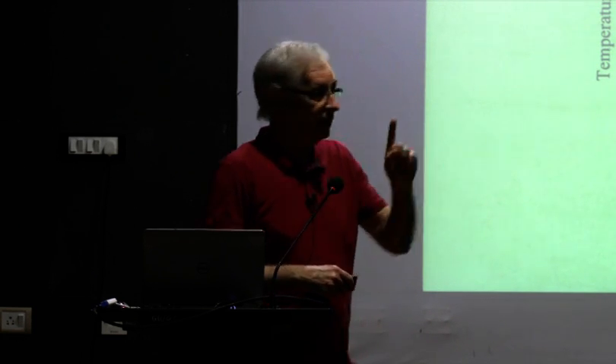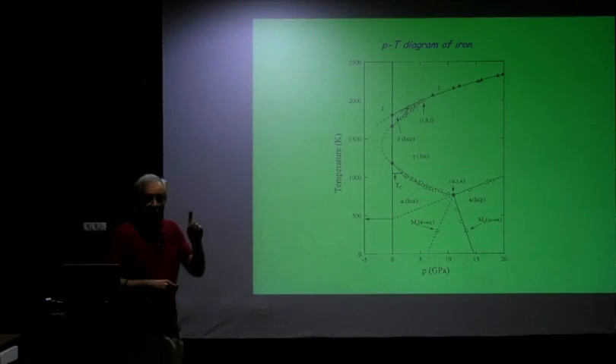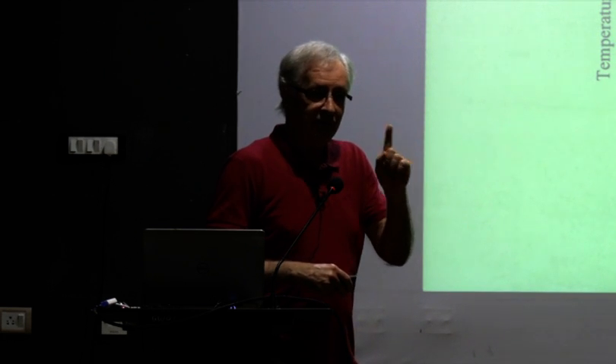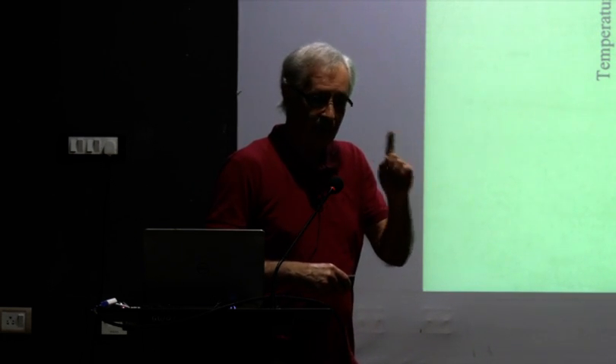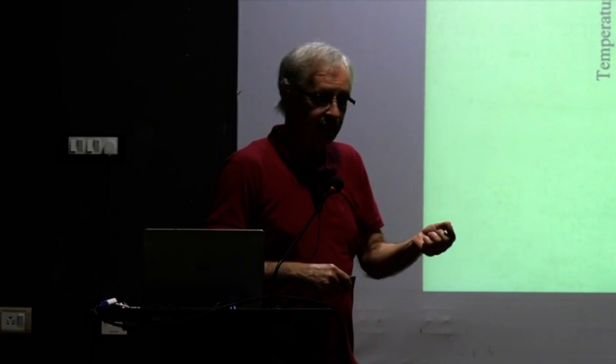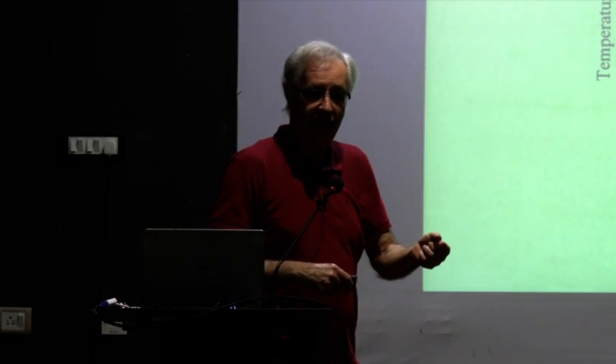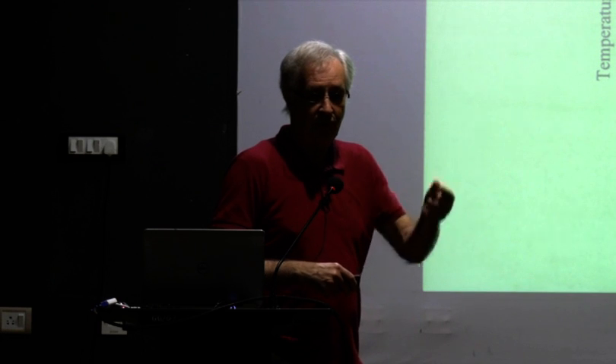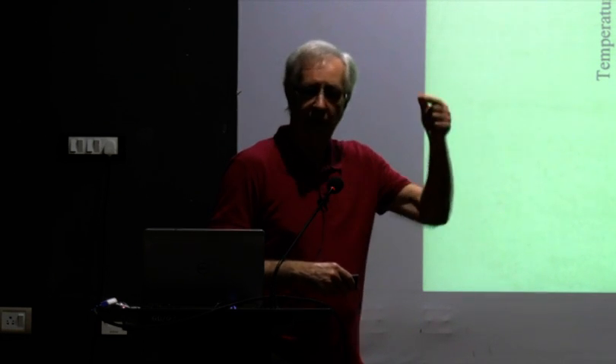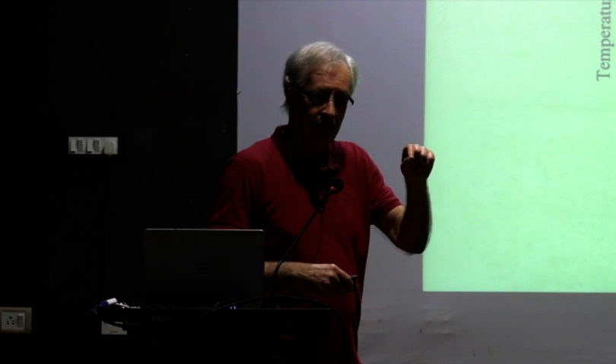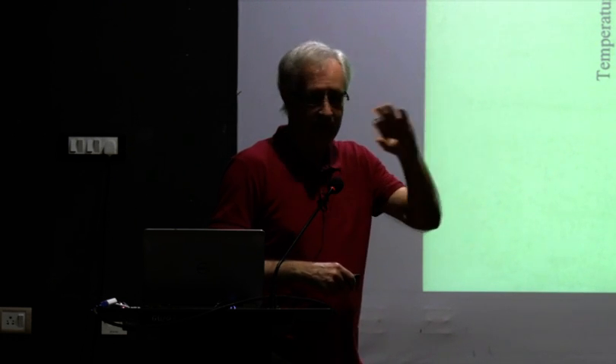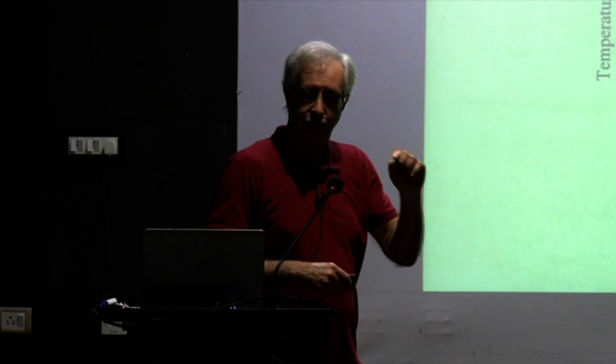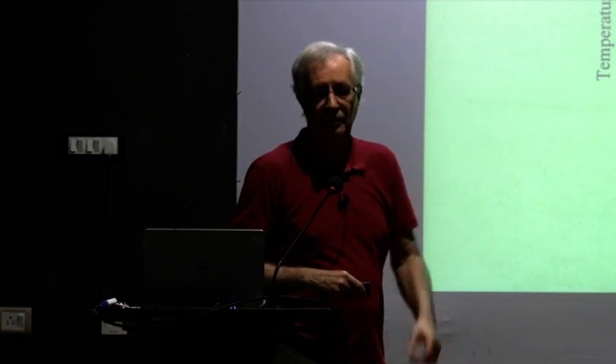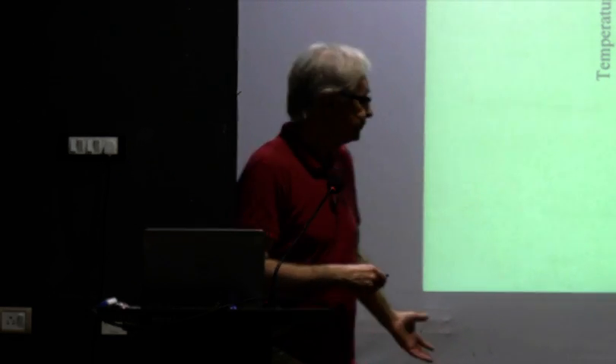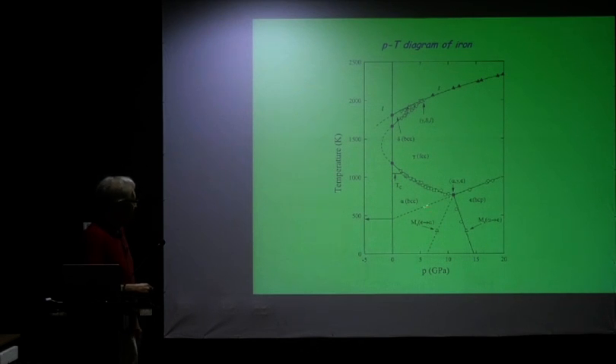So what happens then? It is the magnetism that stabilizes the BCC state. And if we don't have magnetism, the hexagonal state is stable, and everything on the periodic table is better then. So we have ruthenium and osmium underneath iron. Both are hexagonal. And we can show, just by these simple arguments, that iron should have been hexagonal in the event if it were not magnetic. That's one thing we can learn from this phase diagram.